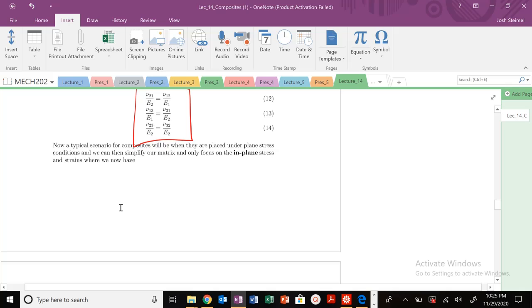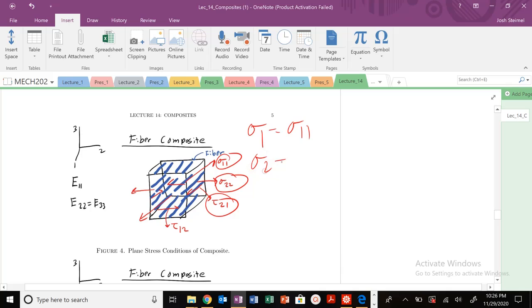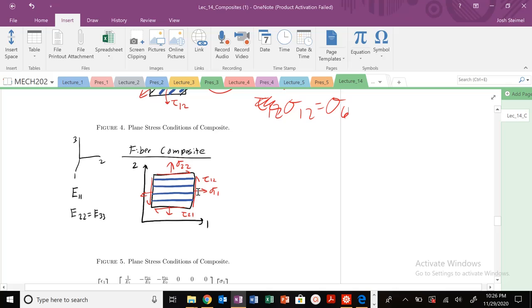Let's consider a simple scenario looking at our matrix in plane stress and strain conditions. I have a stress in the 2-2 direction, a stress in the 1-1 direction, and a shear stress in the 2-1 direction. In the other notation, σ₁ corresponds to σ₁₁, σ₂ corresponds to σ₂₂, σ₃₃ corresponds to σ₃ which is zero here, and τ₁₂ is equivalently this. This is our plane stress configuration.